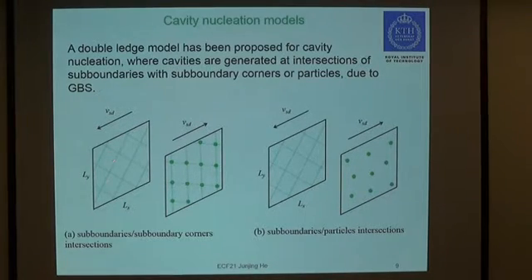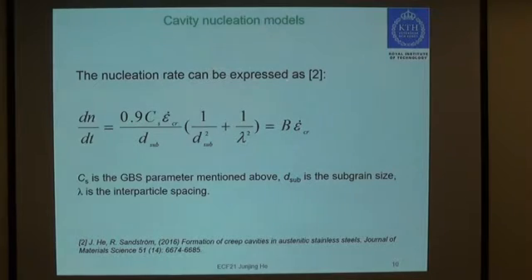The mechanism is like this: when the subboundary corners or particles on one side of the sliding grain boundary meet the subboundaries on the other side of the sliding grain boundary, the cavities will be generated. Based on this mechanism, we have proposed the cavity nucleation rate. Cs is the grain boundary sliding parameter, this is the subgrain size, and this is the interparticle spacing. The final form can be written as parameter B times the creep rate.